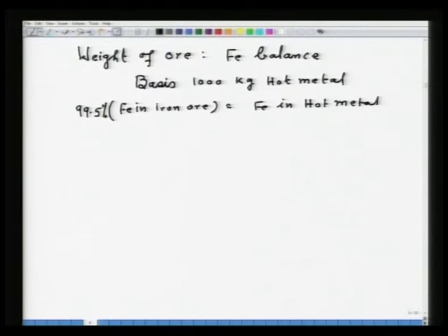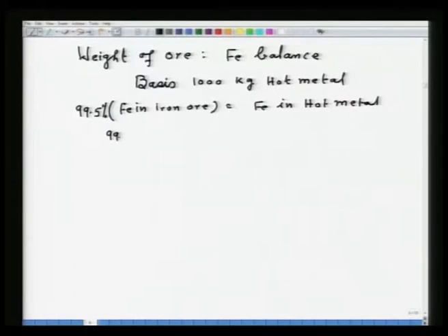Remember, for all iron you have to see the source of input and source of output. In this particular problem iron is entering from iron ore and it is output as iron in hot metal and iron in slag, but it is given 99.5% is reduced. So, our life becomes easier. So, we straight away go 99.5 upon 100 into 112 upon 160 into 0.78 x, that is equal to 927, where x is the kg ore.